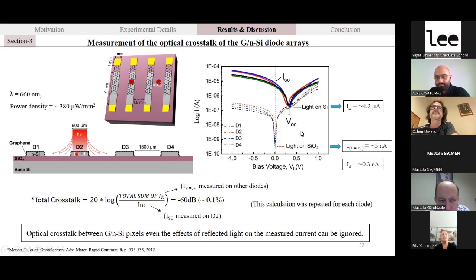So we get the results using this. Here you can see the light on the silicon dioxide case and the light on the silicon. By the way, the active junction. Here you can see both detectors gave nearly the same photocurrent results, with the same open circuit potential value and nearly the same values.